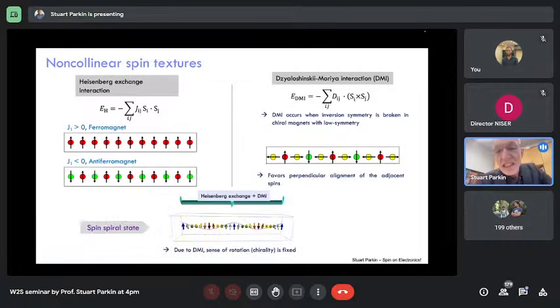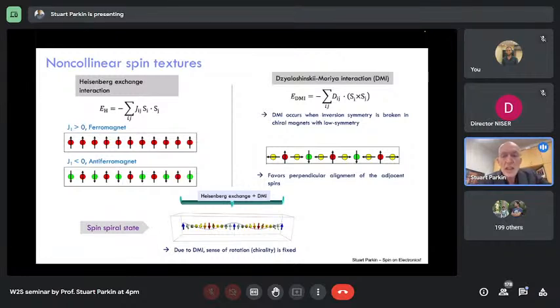So what does that mean? That means going from chiral domain walls, we can actually make more complex textures. On the left-hand side, you see the typical Heisenberg exchange favors the nearest neighbor interaction between two magnetic moments to be ferromagnetic or antiferromagnetic, but I also mentioned this Dzyaloshinskii-Moriya interaction, which is found in compounds where typically you have strong spin-orbit coupling, or at interfaces, as I mentioned, with layers that are spin-orbit coupled. This leads to, as you can see from the top right, an energy that minimizes the energy when the moments are orthogonal to one another.